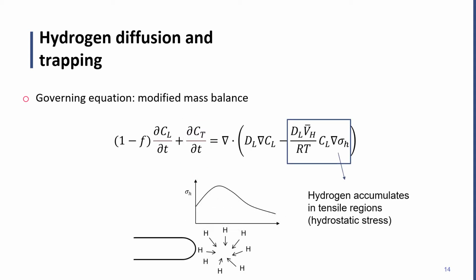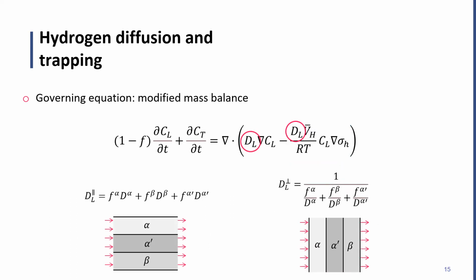An important term here is included within the flux to reproduce hydrogen accumulation in tensile regions, which is very important for fracture. This term is proportional to the hydrostatic stress gradient. Here we are assuming a scalar value for the lattice diffusivity, but to consider anisotropy we could implement, for example, a diffusivity tensor. But here, for simplicity, we are just analyzing two limiting cases. The case where hydrogen diffuses parallel to the phases, which is a much faster situation than the case where hydrogen diffuses perpendicular to the phases.